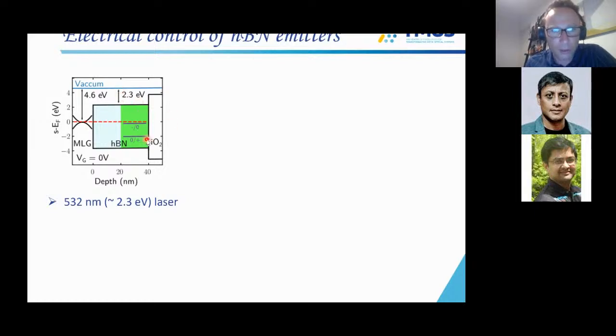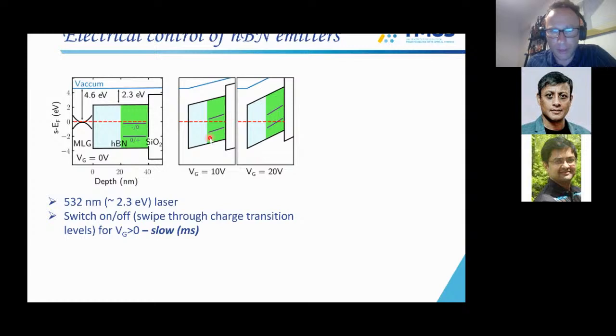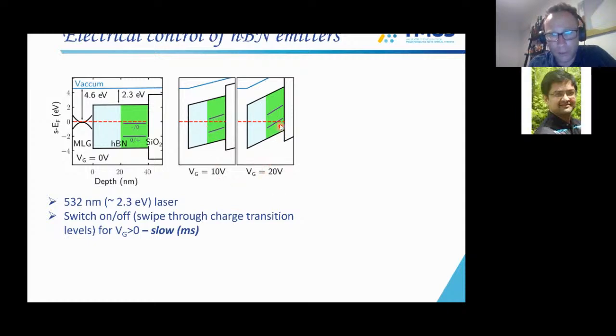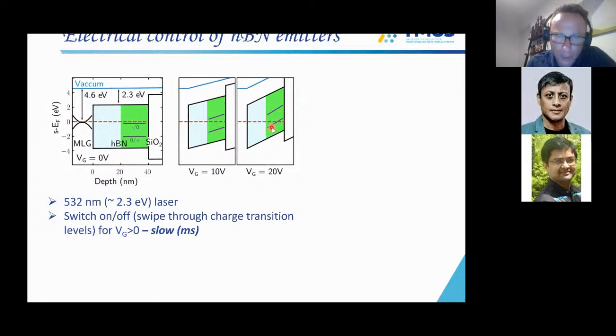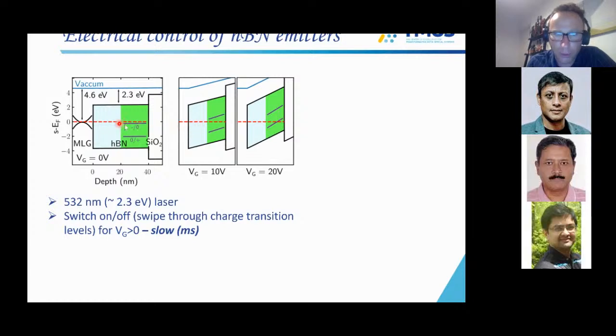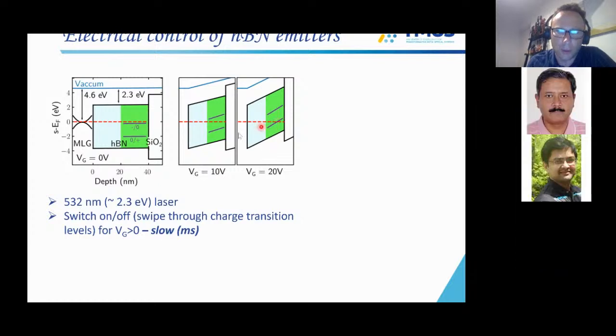So what is happening? In principle, we can take the same energy level system from these carbon emitters, and we can superimpose them here. When we switch to positive bias, there is a band bending upwards, and as we increase the bias, there is even higher band bending. At some point, you shift your transition level from 0 to -1 or -1 to 0. But as you increase the bias, you actually cross a second charge transition level. And so this explains why under 0 bias, you have no emitters. Under low bias, you have some emitters that are turning on. And under very high bias, you shift them off again because you're going to a different charge state.